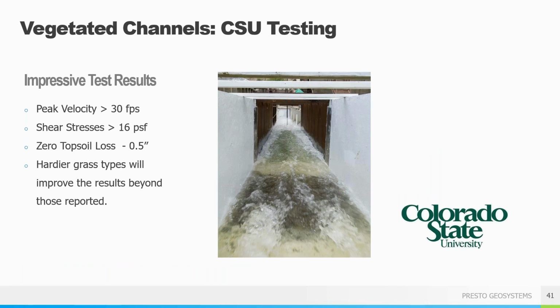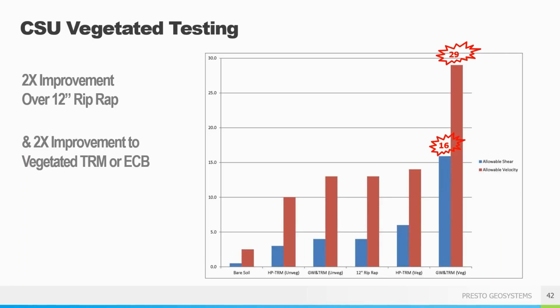We tested this vegetated solution covered with a mid-grade TRM, not one of the newer high performance TRMs, and received great results. You can see that it was able to withstand 29 feet per second and 16 pounds of shear, which is more than twice the hydraulic resistance of 12-inch riprap and about double the performance of the new high-performance TRMs alone. It works so well because the TRM provides a cover for the GeoWeb so the cells won't scour out during high flow. And what the GeoWeb does is confine the soil directly below the turf reinforcement mat so the system won't fail when saturated. In an unvegetated condition, GeoWeb will also improve the hydraulic performance of a TRM alone by 30%.